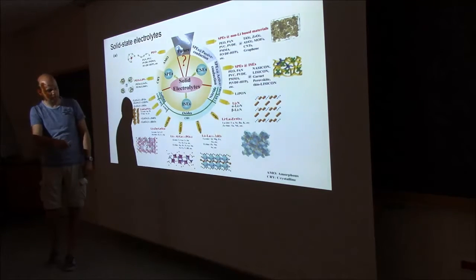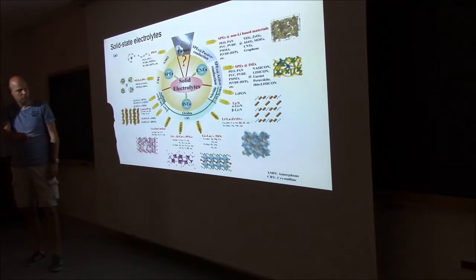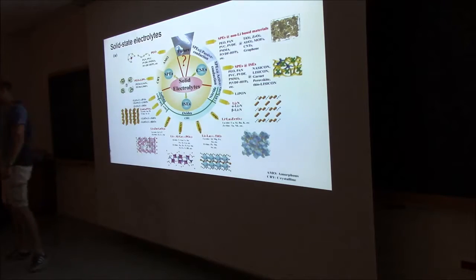But you have here lithium lanthanum titanate, this is perovskite. Lithium lanthanum zirconate, that's a garnet, which works well. And for instance, you also have your lipon. Lipon is an amorphous material. People use that, but it doesn't have the best performance. What we like to do is to focus on these two, the garnets and the perovskite. Garnets have a crystal structure which is about 12 angstrom. It's huge. So if you think about the textural relation, that's all very difficult. We do study this, but it's not that simple. What we have been focusing on is the perovskites. It's a titanate. You can think about, okay, then you can find nice matches with the materials I've shown you before.